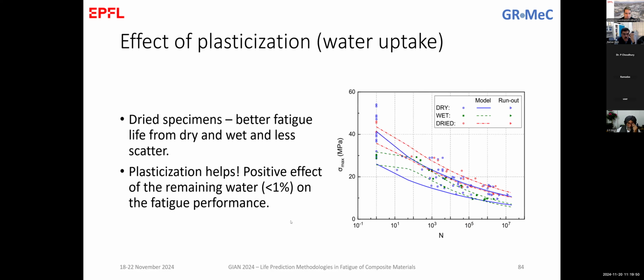So if we jump to the results, we see that, for example, here you have the blue ones that are the dry ones, the wet ones, so those that were immersed in water are the green ones, and the dried ones are the red ones. And the curves that you see here are the 5 and 95% curves that I drew based on the ASTM suggestion. So actually these curves every time show the range where we can expect 95% of the specimens of each class to fail. And what we can observe here is that the dried specimens are the best among all. So those specimens that were wet and then dried are the best among all.